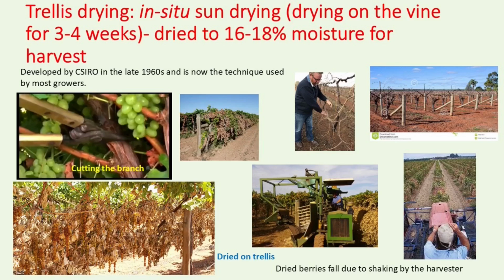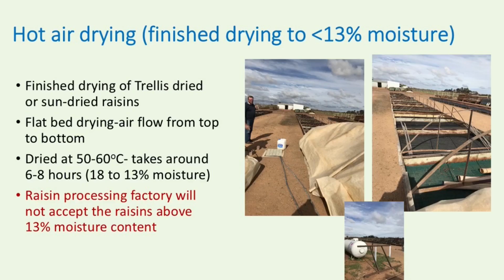semi-dried raisins. When they dry, the moisture is about 20, 22, 25% at the time, but they have to finally dry to 13% moisture. They use hot air drying for final drying before it goes to the processing plant.